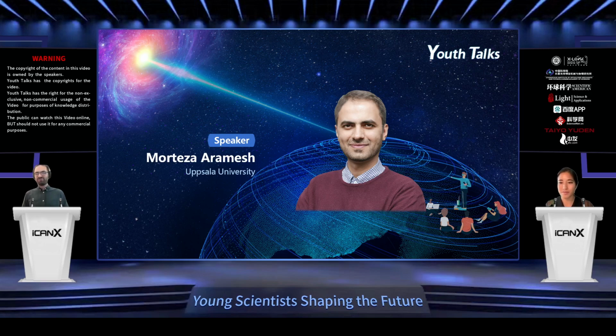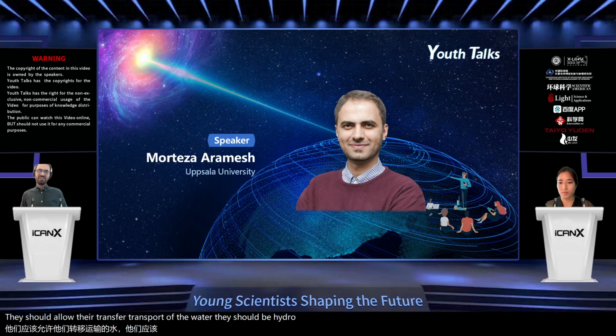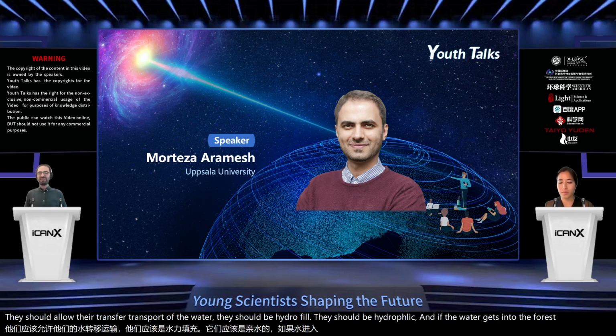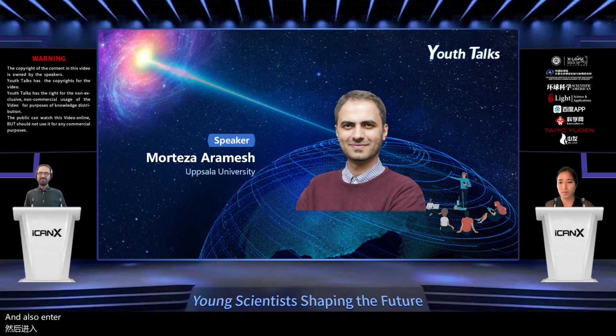Very good question. No, there are no treatments required. It's a very simple process. Cells start to make those protrusions as soon as they are placed on top of the surface structure. One thing that could be quite critical in this process is that the pores should allow the transport of water. They should be hydrophilic, and if the water gets into the pores, then that means the cell can also enter inside. But there is no surface chemistry required.